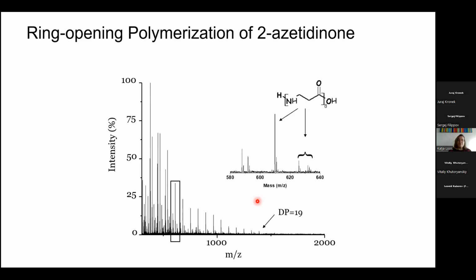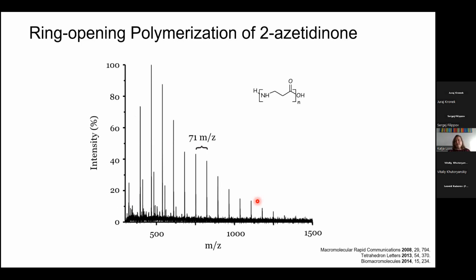And if you zoom in on one of these peaks of this multiplet, you also see it's a classical polycondensation, because you see linear chains and also the rings. But we found a lot of nice ways also to remove the rings. For industry that would be important, and also if we put them later in the extruder to do the post condensation, the rings would hurt our process. But there are many easy ways to remove the rings, and it works very well. And yeah, we worked a lot with this reaction, but I don't want to show you all the results. It's also a bit older already, but this was our first approach to polyamide synthesis.